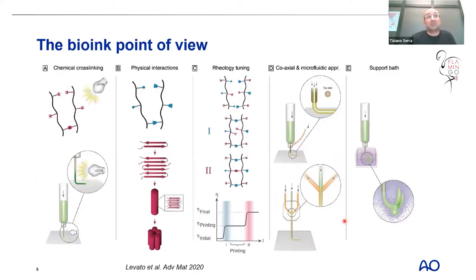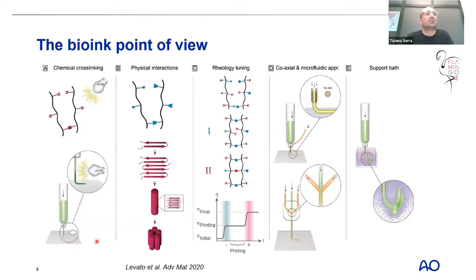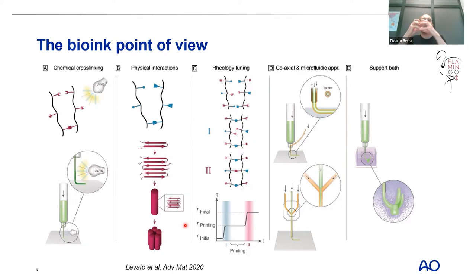An important perspective is the material perspective — the generation of bio-ink. When we call bio-ink, we consider a hydrogel precursor ink that will be cross-linked and is loaded with cells. The material should be liquid during extrusion and then cross-linked after extrusion through light, chemical, or enzymatic cross-linking. There is also a way to tune material composition to achieve physical entanglement — a spaghetti-like construct extruded through a nozzle where polymer filaments remain connected.